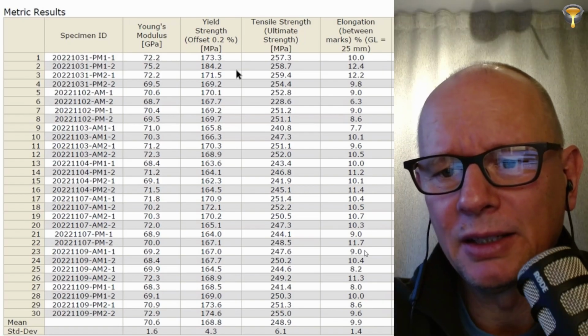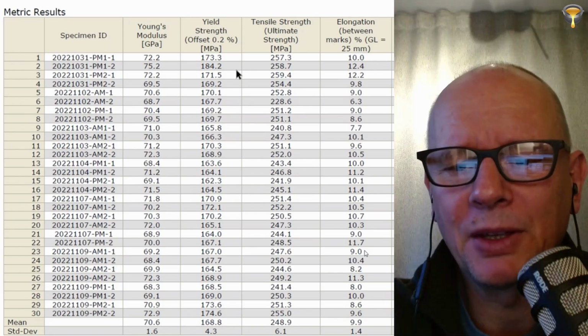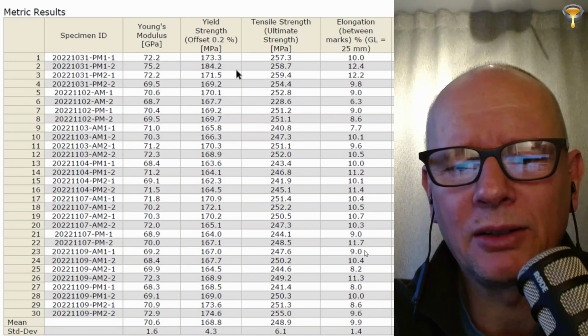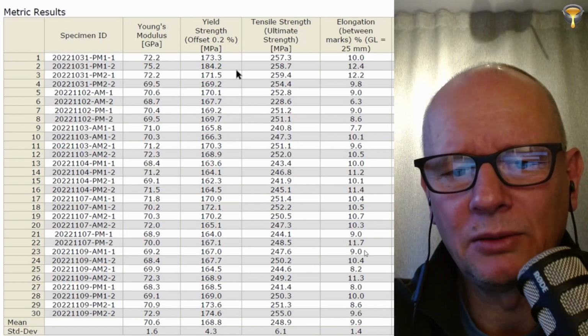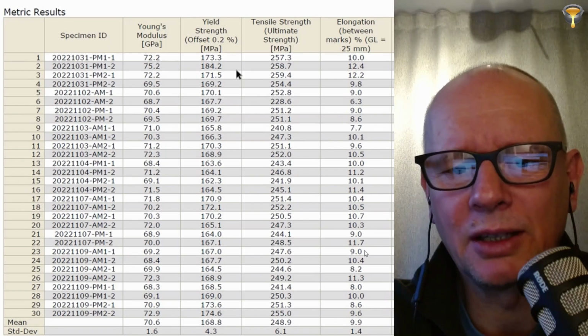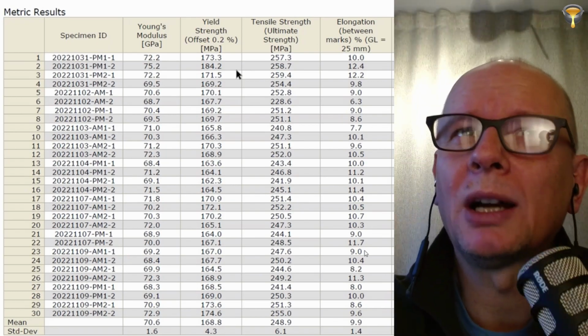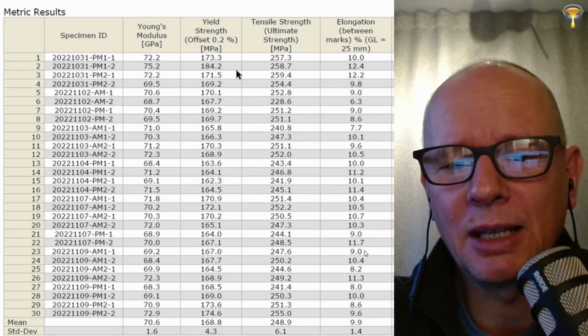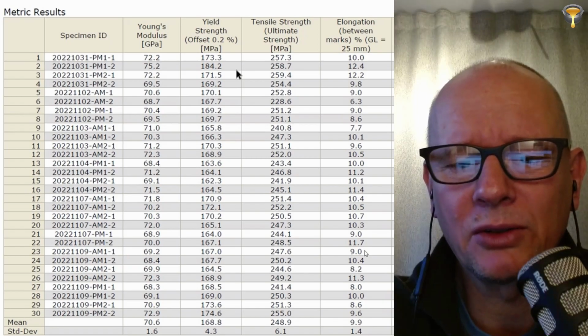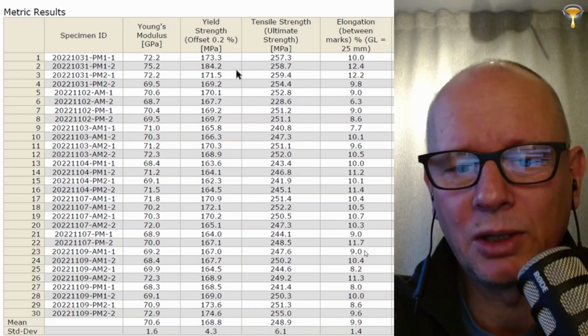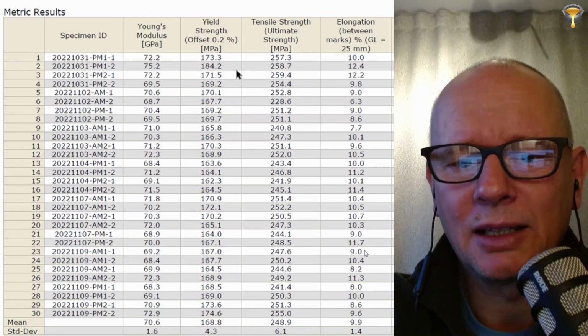It's not that nice. But again, talking about this hinge pillar now, another aspect I would like to give, and if you're working with structural casting, you should probably listen pretty carefully, because there are a couple of things that happen when you use Rheocasting. We have a picture here with a table that shows yield strength, tensile strength, and elongation. If you look at the numbers, you see that they are very, very centered, meaning that the spread, the standard deviation of your numbers, is very, very narrow. So why is this important? Well, with Rheocasting, you get the same properties in all directions, whether transverse to the flow direction or aligned with it. And also that standard deviation is very low.